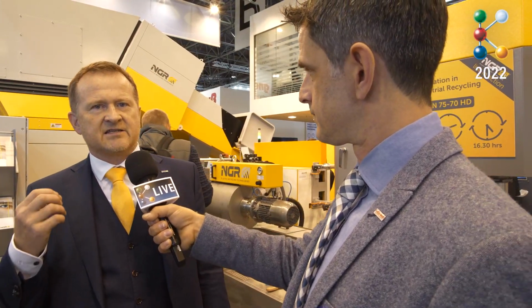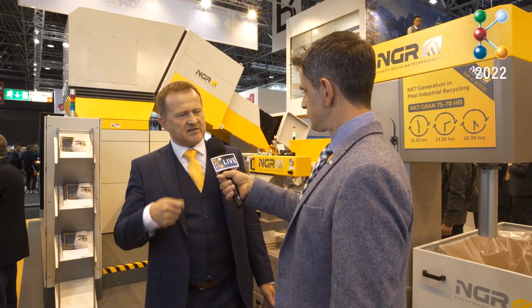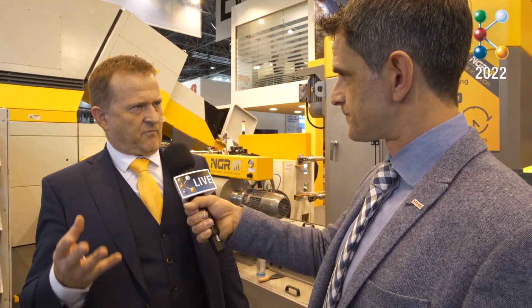The LSP Technology improves PET, which means increasing the IV, the viscosity, as the polymer chains get prepared, and the material gets cleaned under vacuum. Therefore the material is excellent for usage in beverage packaging again, or in different usages like fibers or sheets and such applications. So NGR is doing recycling technology in nearly every field of polymer, in nearly every position in the value chain, to contribute to circularity, to increase the acceptance of plastic polymers, and to work for a better future.